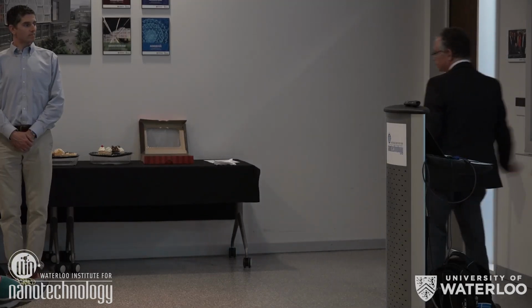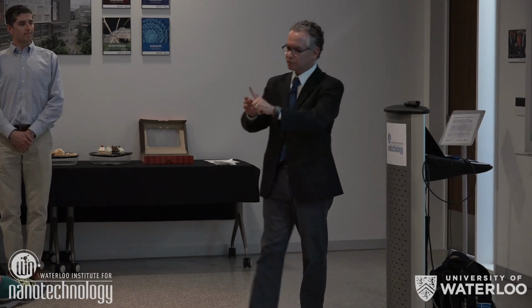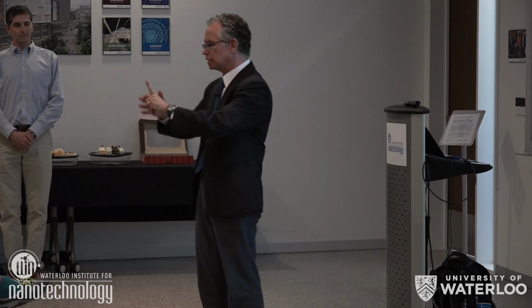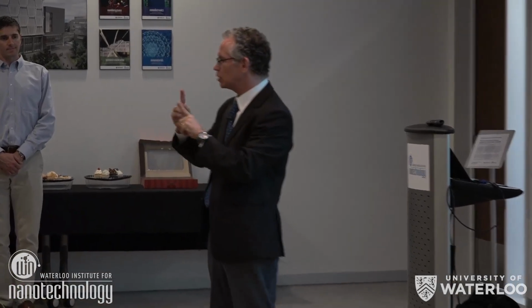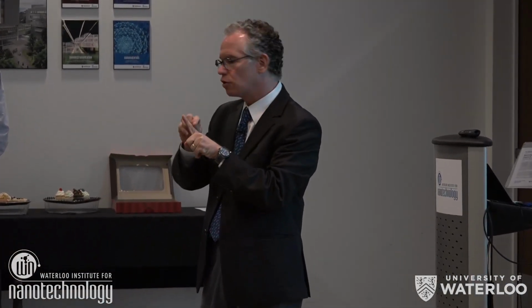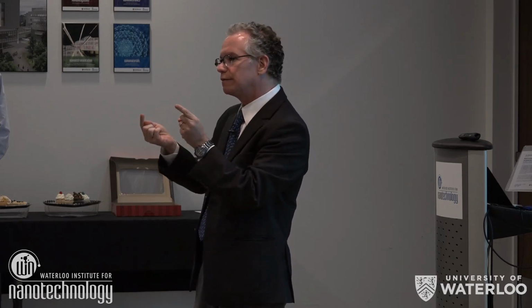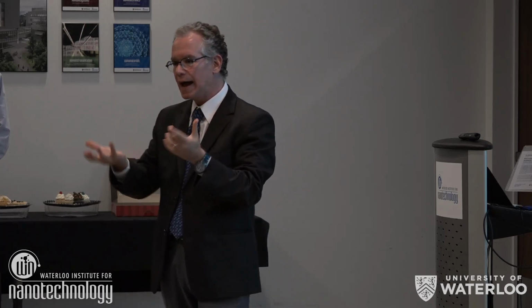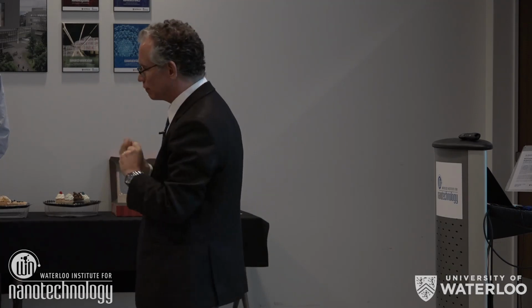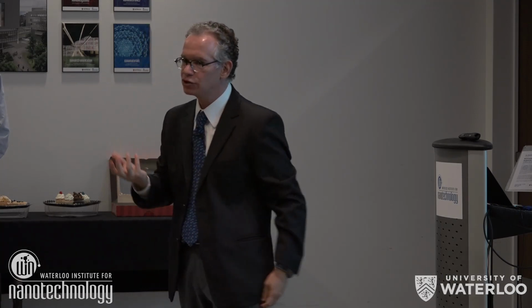You manage to develop a system which is isolated, a magnetic nanoparticle, so you have an anisotropy, you have relaxation time, and so on. But then you have this set of others, and they interact through dipolar interactions. And it's not only one or two, there are thousands and thousands, and these dipolar interactions can affect the behavior very strongly. So the dipolar field in some way acts as an extra temperature for the system. Yeah.